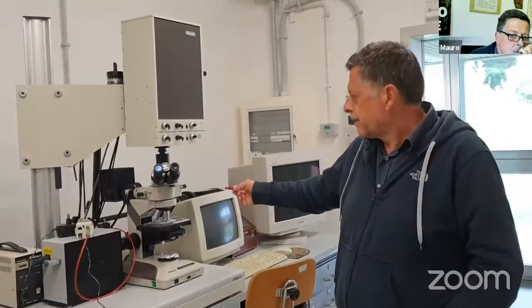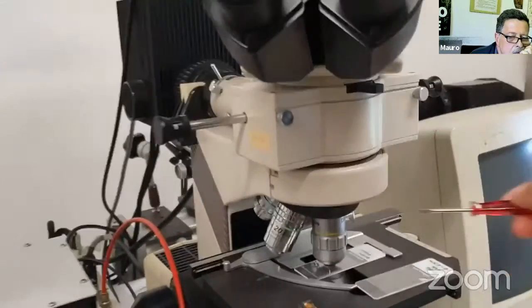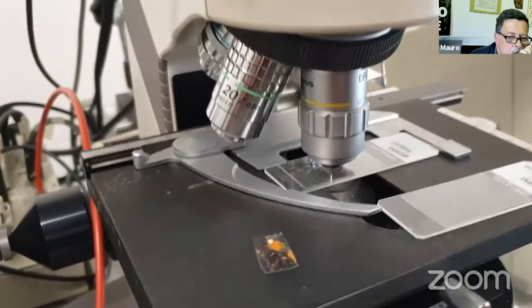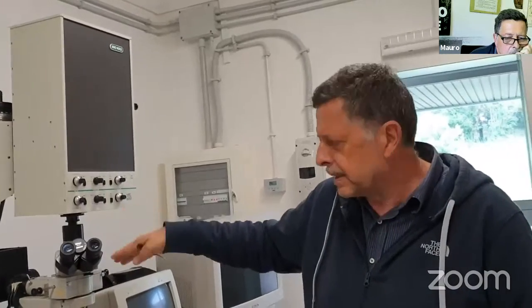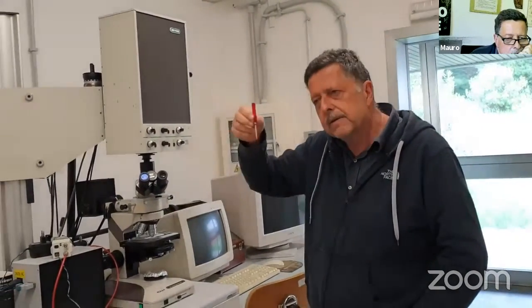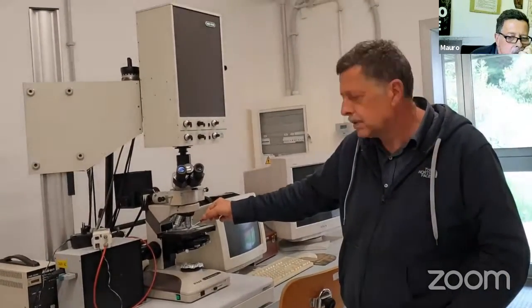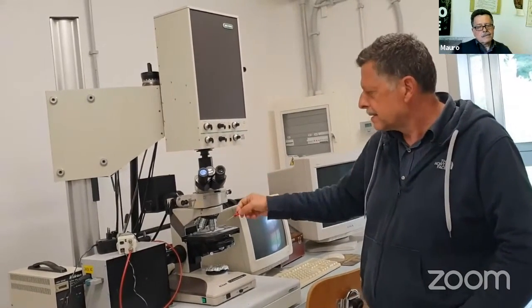Still on the luminescence experiments, we have another experiment here, which is a confocal laser scanning microscope. This is a luminescence microscope where the sample is placed on a glass slide, and the laser light is sent to the sample by a system of mirrors which can vibrate. In this way the laser changes the angle on the objective, and then the laser light scans the position of the sample. So each time the sample is illuminated by the laser, it is supposed to emit light by luminescence. Luminescence is collected by the same objective, and then you can reconstruct a luminescence map of the sample.